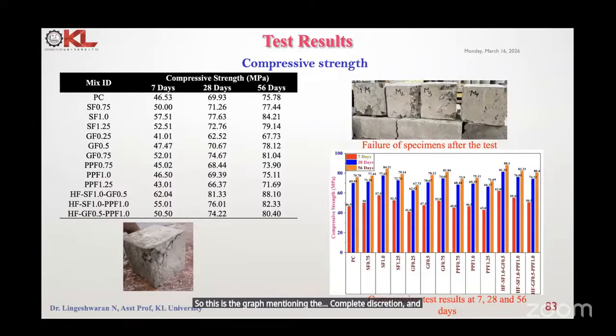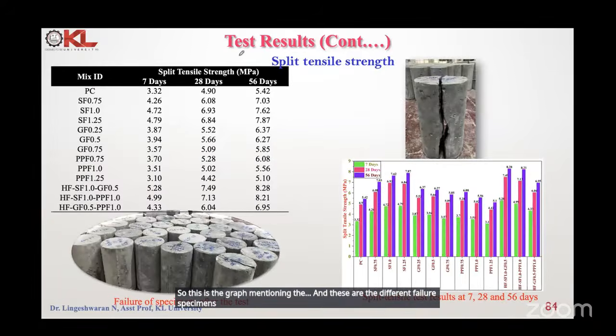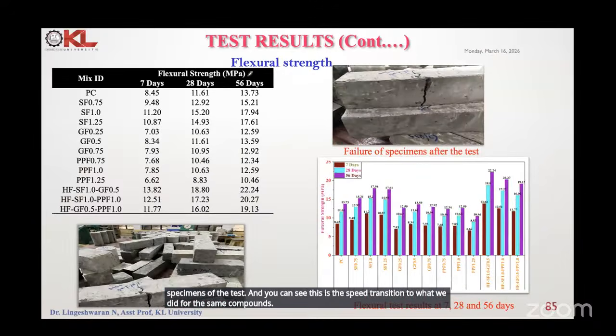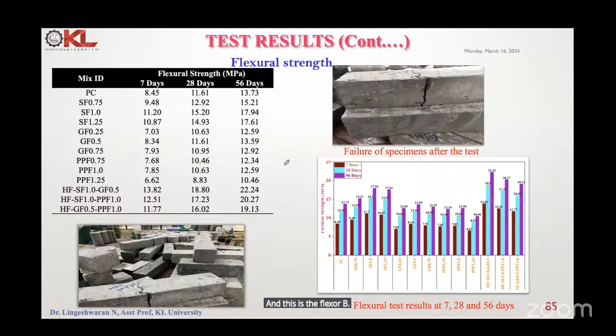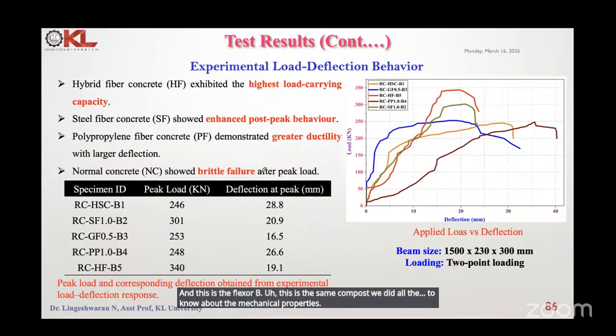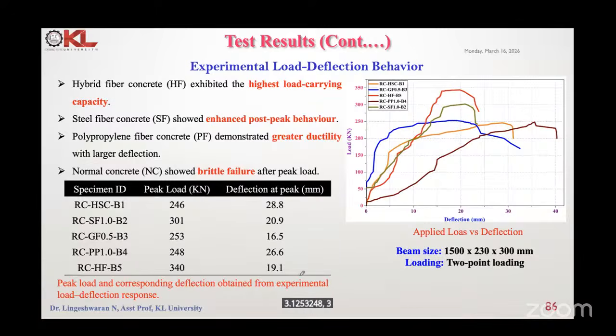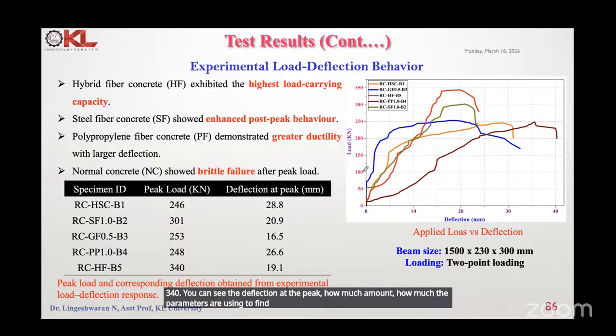And these are the different failure specimens at the test. You can see this is the split tensile strength we did for the same mixes, and this is the flexural beam. We did the same mixes to know about the mechanical properties. Even stress-strain we also did. And finally we found the load versus deflection. You can see here the beam ultimate loads are 246 kilonewton, followed by 301, 253, 248, and 340. You can see the deflection at the peak under two-point loading. So this is the result we got from the last case.